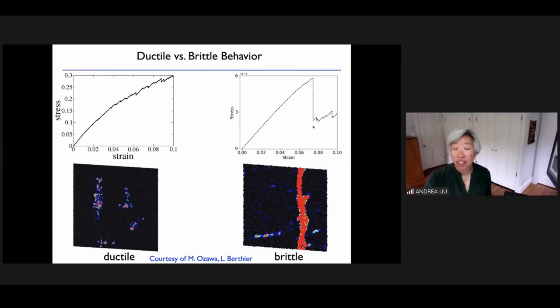And when you see that large stress drop, if you look at the accumulated displacement of the particles during this process, this is what it looks like over the strain range in the ductile system, but in the brittle system, you see this very sharp shear band. So that's a big difference.